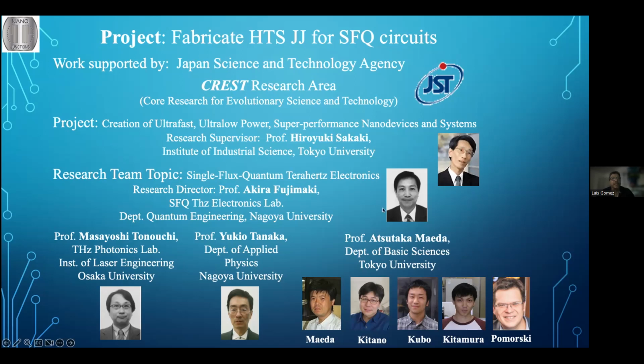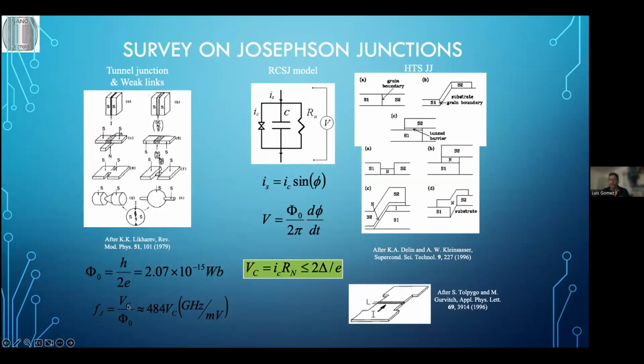So anyhow, we coincided in Japan in 2005, and we were involved with Professor Fujimaki in doing terahertz electronics. He's an expert on single flux quantum technology, and by using a certain type of Josephson junctions that have a very high characteristic frequency, on the order of terahertz, we can create systems that oscillate at that frequency. I will show you this equation again: the characteristic voltage we see in the junction, which is the product of the critical current by the normal resistance. If this is high enough, then you can be at almost 500 gigahertz, or if you have 1 millivolt or higher.